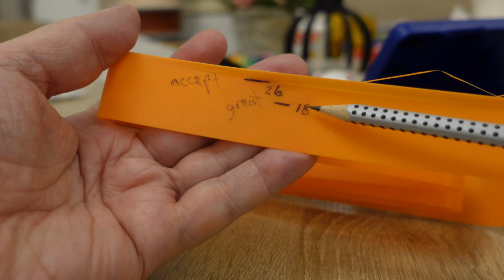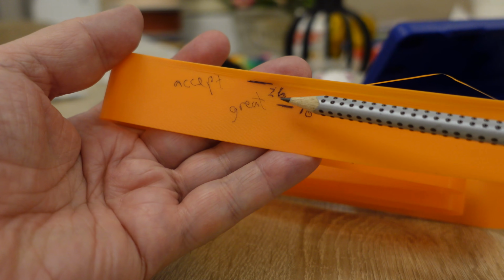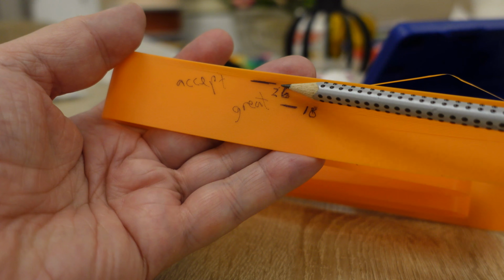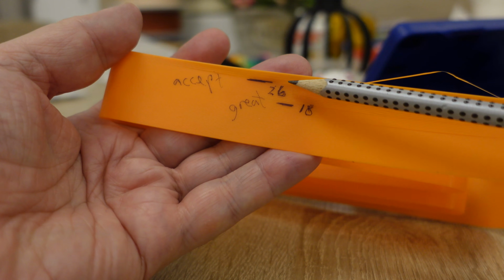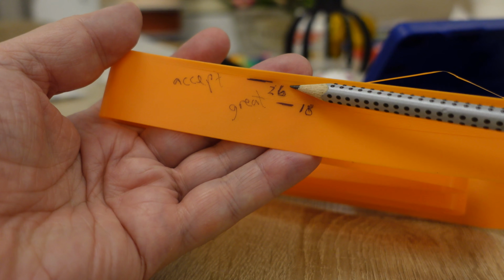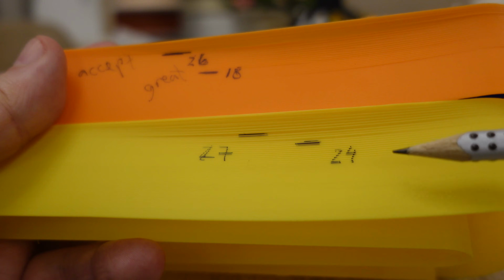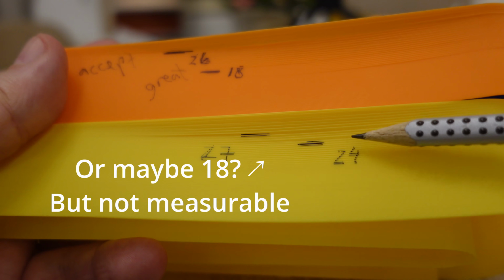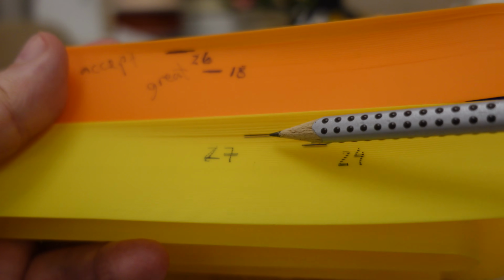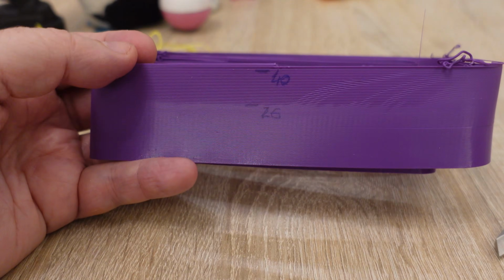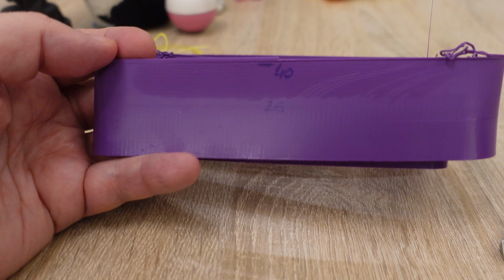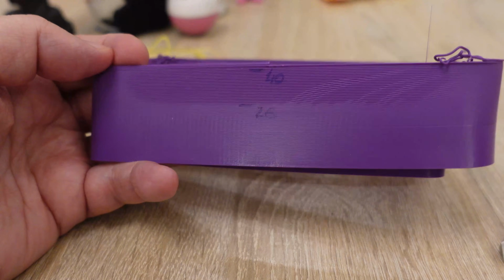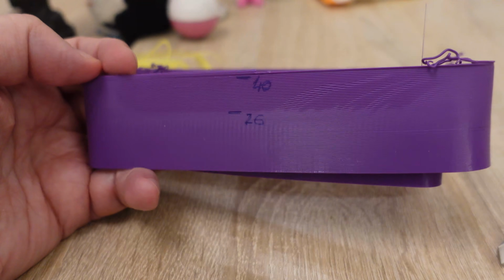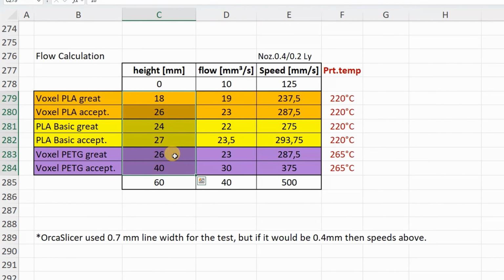Until this point, 18 mm, the quality is great, and until this point, 26 mm, the quality is acceptable, but I could measure some minimal under extrusion. And with PLA Basic these numbers are 24, great extrusion, and 27, acceptable. And in this case, great until 26 mm and acceptable up to 40 mm. These are those heights, and this is that flow rate at that height.